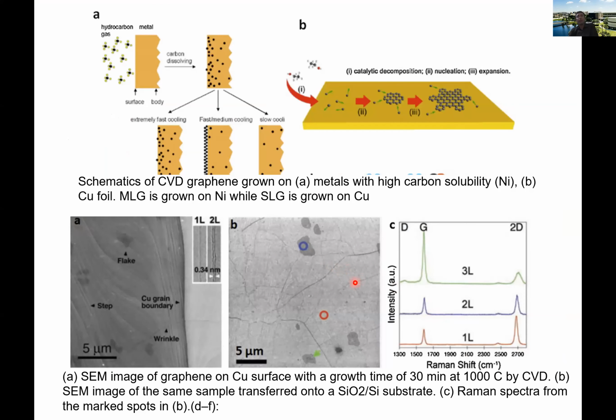And you know you have grown single layer graphene by doing a Raman signature. You measure the Raman. This is the easiest way to find out that you have graphene. You have a 532 nanometer laser, you shine it on the sample, and you get Raman signature peaks specific to graphene. And this is the scanning electron microscope image of the graphene.